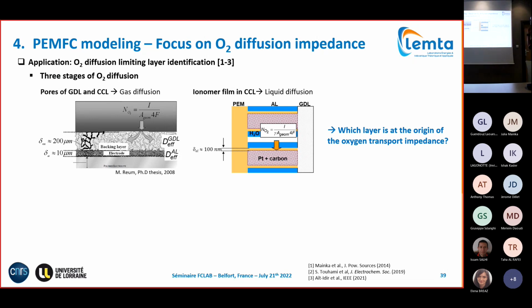To give you another example of what you can do for analyzing spectra, let's focus on oxygen diffusion impedance, meaning low frequencies. Physically, oxygen diffusion occurs in 3 different stages. The first two stages are primarily gaseous oxygen diffusion through the pores of the GDL, then through the pores of the active layer, or smaller pores, until accessing the active sites. Finally you have diffusion through the small ionomer layer covering the active sites.